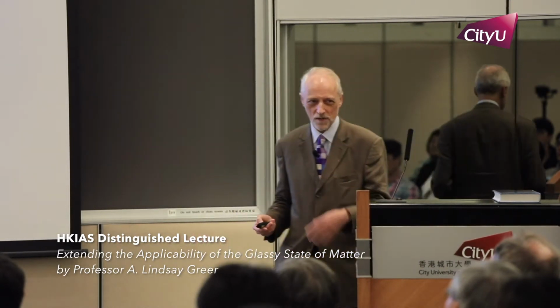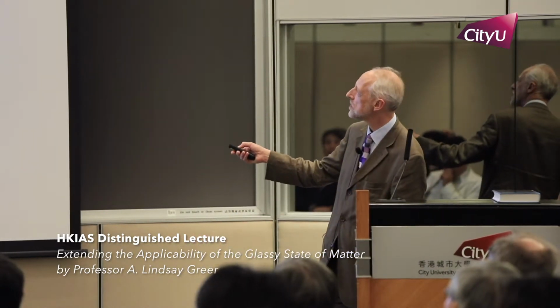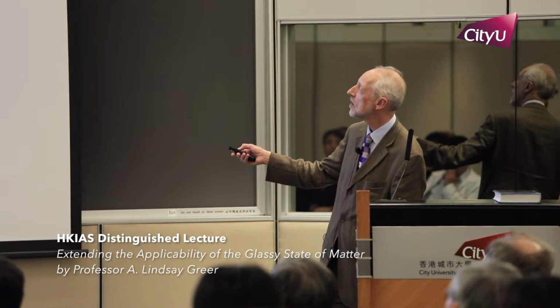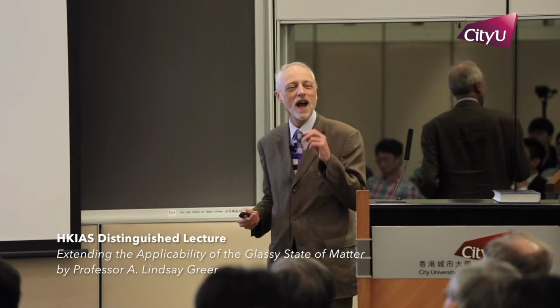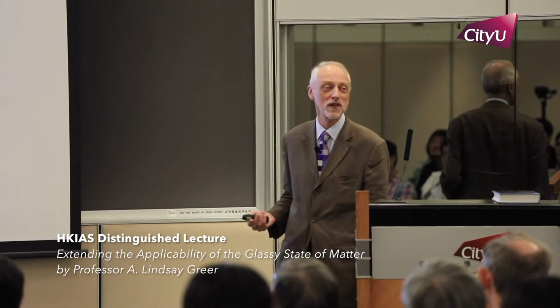If you were melt spinning at 1,000,000 degrees per second, you'd form that glass, which has a certain enthalpy. If you were forming it in bulk, you'd come down this line and you might be here. We have raised the energy of our system. We can easily plot that on this chart. And it's really quite straightforward to work out, if you wanted to make this high energy glass by cooling the liquid, how fast would you have to cool the liquid? And the answer is about 10 to the 10 degrees per second.